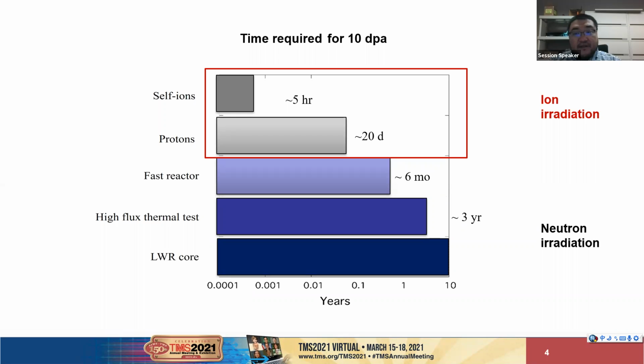While not a complete surrogate for neutron radiation, it does allow the exploration of potential microstructure states and their influence on properties. We know that ion radiation is not the substitution of neutron radiation, but it can do a lot of things. For example, we can use ion radiation to test and eliminate the candidates that are not durable and reliable under radiation. If the sample cannot survive under ion radiation, we believe that it could not be used in the neutron irradiation environment. Also, ion radiation can help us to reveal the mechanism of radiation damage in a simple and easy way as well.